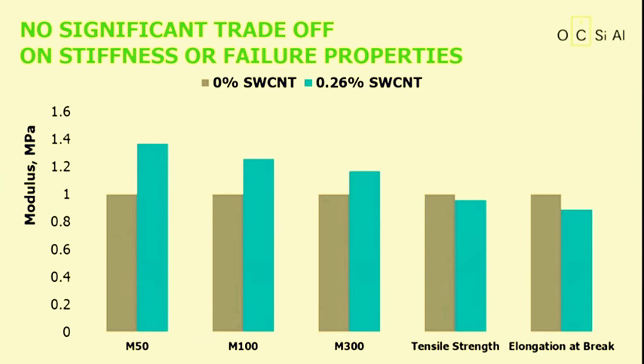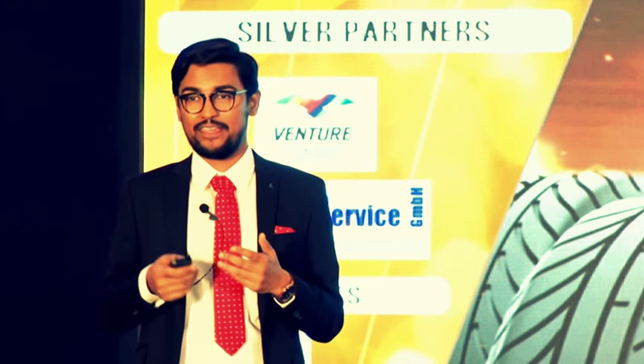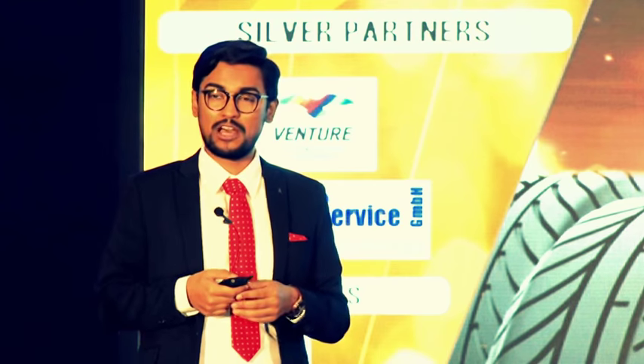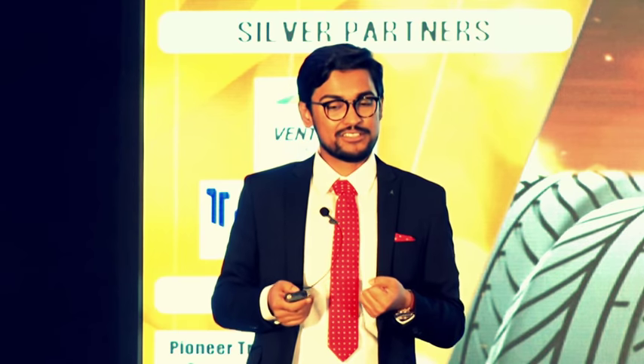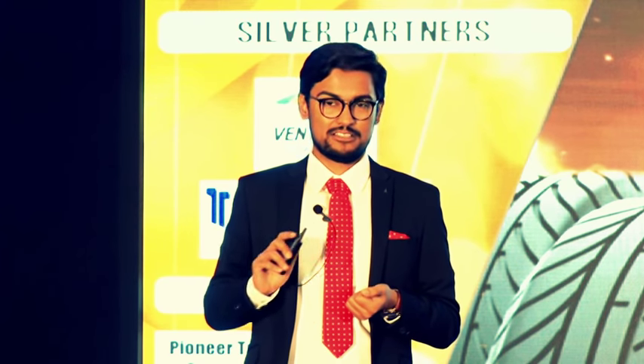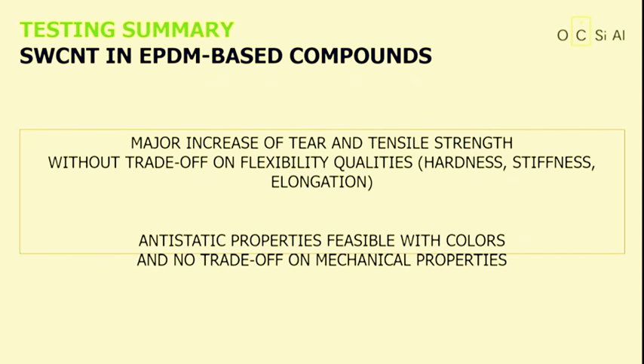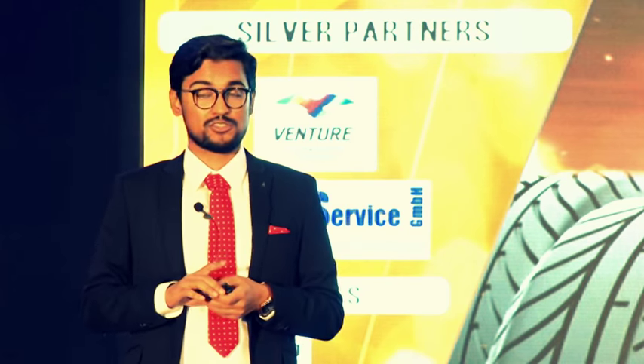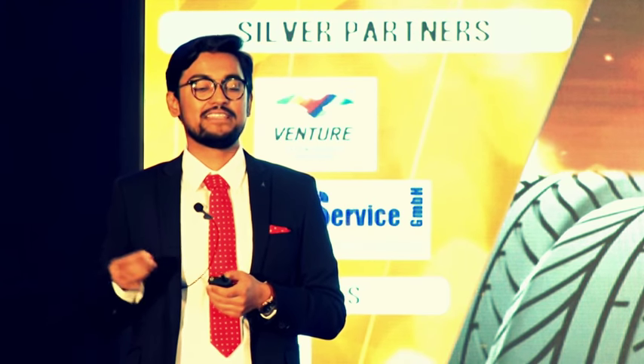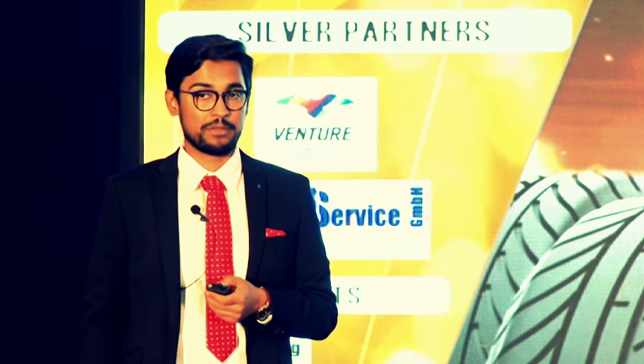Again, there was no significant trade-off which you had to do by adding single-walled carbon nanotube as in comparison to the carbon. You add carbon, the compound becomes hard. You add carbon, the elongation at break decreases sometimes. But here you can see the effect was not that adverse. So the summary of all those tests was there was a major increase in tear and tensile strength without a trade-off on flexibility qualities like hardness, stiffness, and elongation. Then again, you get anti-static properties also with the possibility of adding in color, again without any trade-off on mechanical properties.